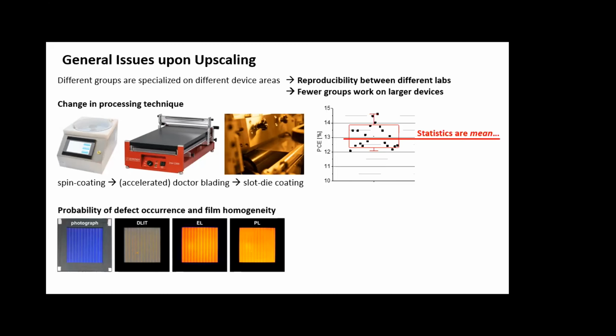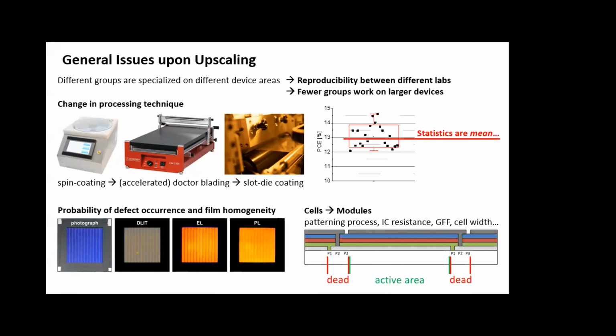So in the case of small area devices, defects which destroy and completely shunt your devices, say 5% of your devices, that's just a yield thing, and they are basically discarded. If you go to large areas, you cannot discard those, and what just lowers your yield on a small device level lowers your performance on the large area device. Also, the film homogeneity is harder to obtain if you increase the area.